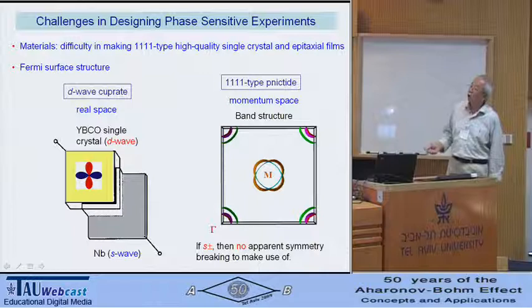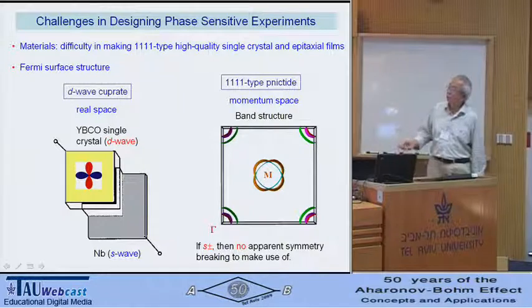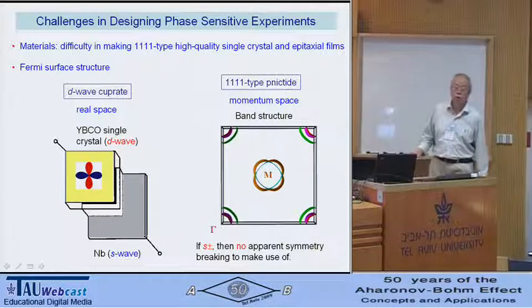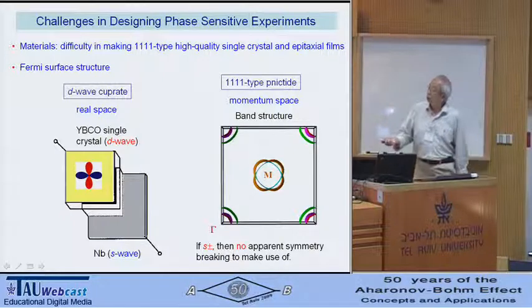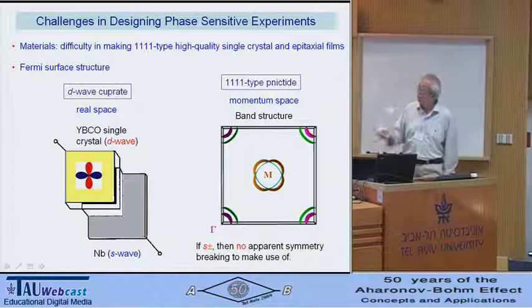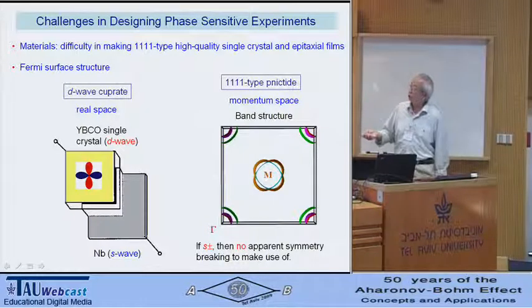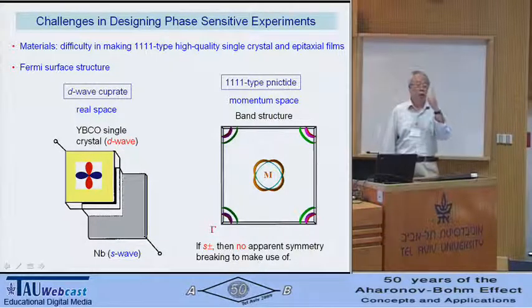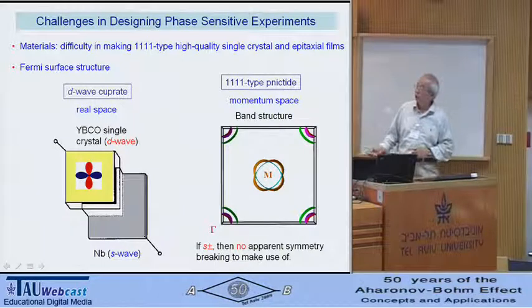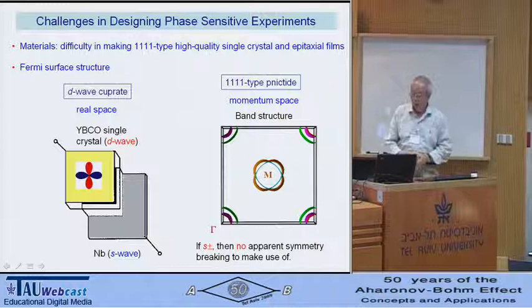Let's recall the early days when we did the D-wave experiment, for instance. If you have a D-wave material like this, and you make a corner junction using an S-wave material like niobium, which is a singular even parity regular S-wave superconductor, then you go from this direction, the current goes this direction, so plus to plus, but you go the other direction, it's minus to plus. So as you circle around this corner, what do you get? You get a sign change once. So you expect there will be a half flux quantum here. And that's indeed the case.